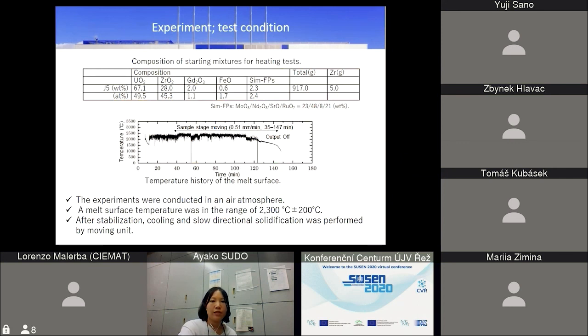And this is the temperature history of melt surface during heating test, and the experiments are conducted in an air atmosphere. And the melt surface temperature was in the range of approximately 2,300 degrees C. And after stabilization of the melt temperature, the sample stage was moved below, and cooling and slow directional solidification was performed by moving it. The sample stage was moved below, and melt was solidified from below slowly.